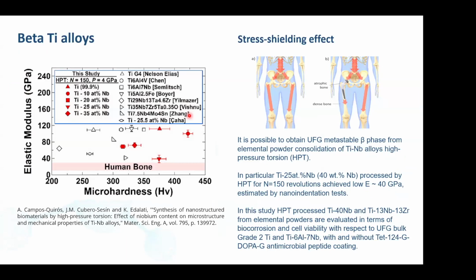Okay, so moving a little bit further into alloys, and I said we did some work on beta titanium. One of our most important results revolve around the titanium 25% atomic percent niobium, that's 40% in weight, synthesized by the elemental powders. So usually, as I said, the stress shielding effect means that if we put an implant of the high Young's